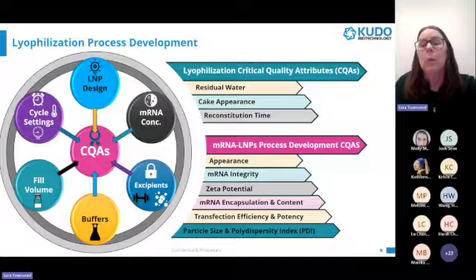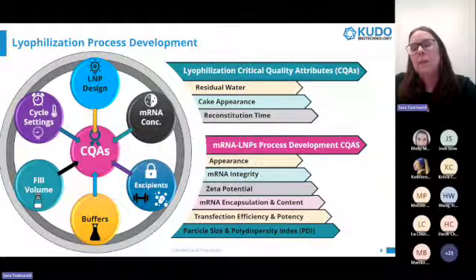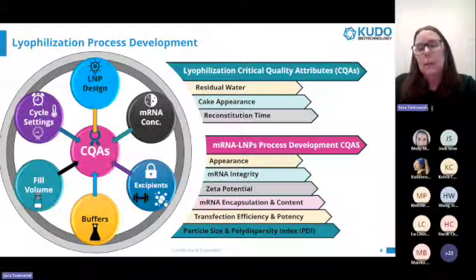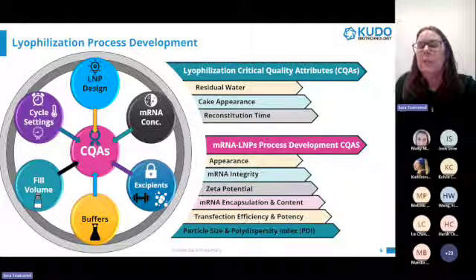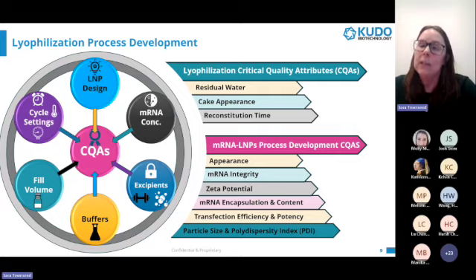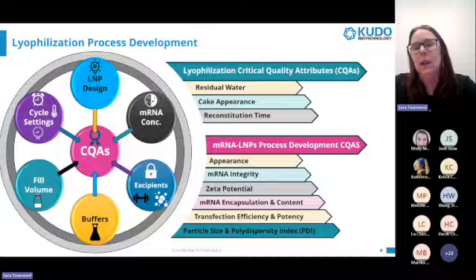Polydispersity index, or PDI, is a measure of the range of particle sizes in the sample. The more uniform the sizes, the smaller the PDI. Typically, larger particle sizes are thought to be less stable and can be more prone to mRNA leakage. mRNA leakage can be seen by lowered mRNA encapsulation efficiencies.